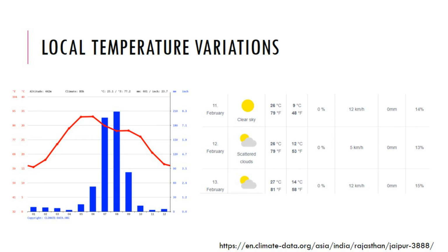For example, if you begin the coating of the component in the early mornings where the temperature will be 9 degrees Celsius or around that, then at that time the coating on that part of the component will get cured slowly at first. If you continue coating that component and in the morning the temperature increases to 23-26 degrees Celsius, that part will get cured faster. So now there are two regions in the same component where the coating is getting cured at different rates.